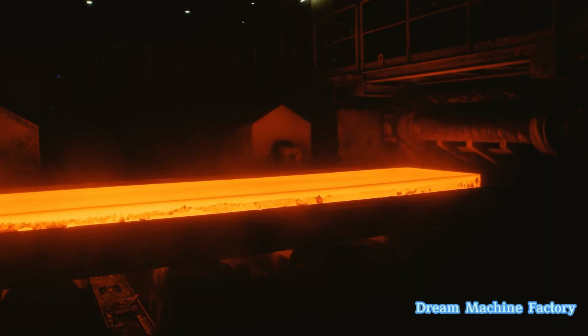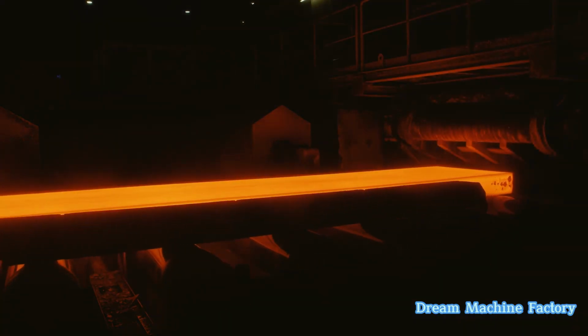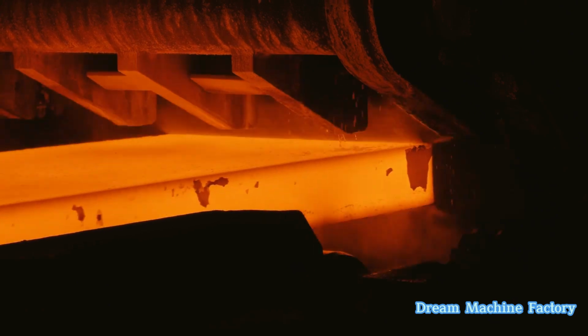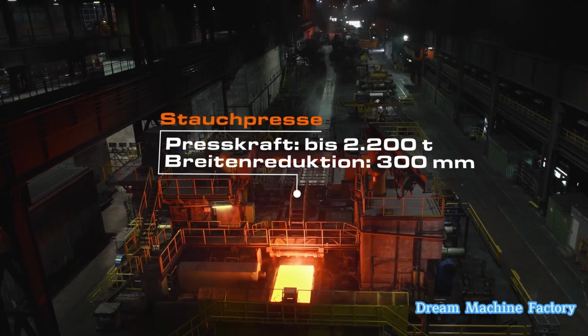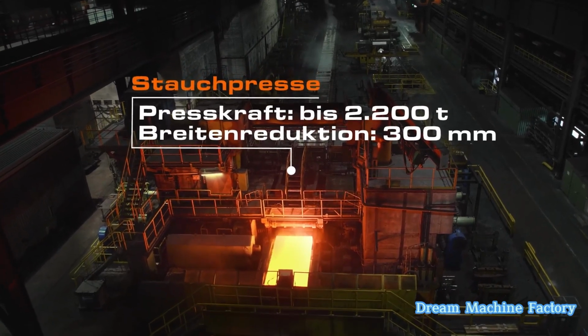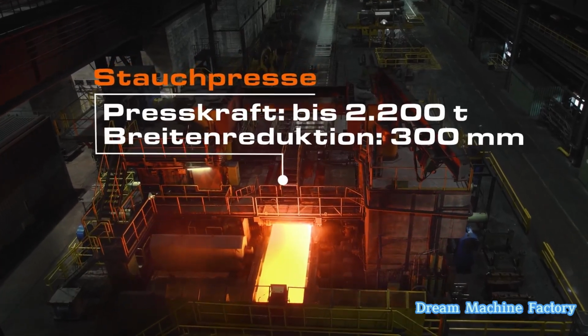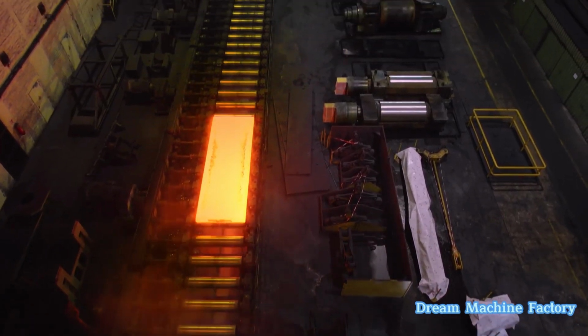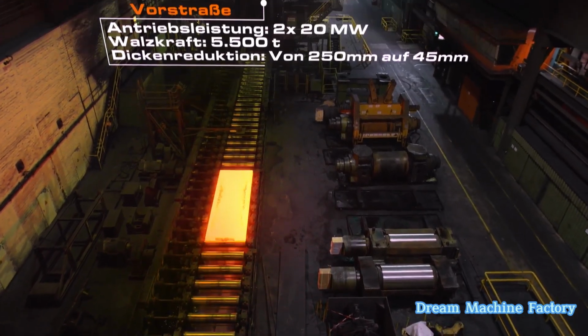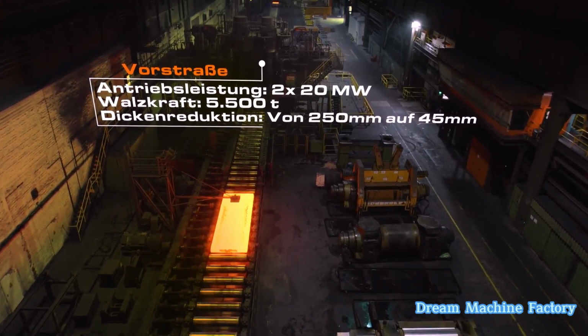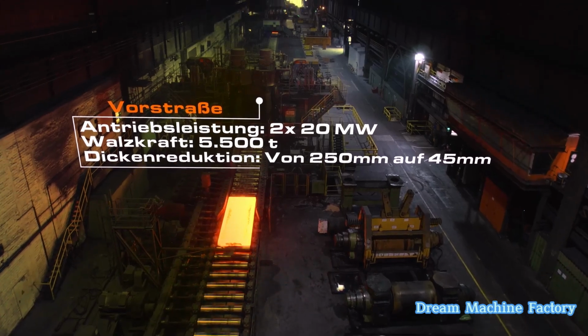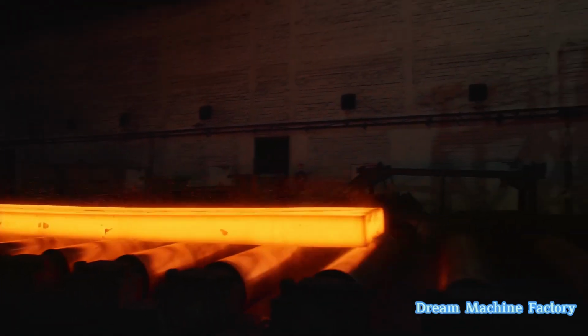Once heated, the slabs are transferred to the rough rolling mill. Here, they undergo an initial reduction in thickness and width, using presses capable of exerting up to 2,200 tons of force. The width of the slabs can be reduced by up to 300 millimeters during this stage, preparing them for further refinement. The semi-finished slabs move to the finishing mill, where they are further rolled to achieve the desired thickness.